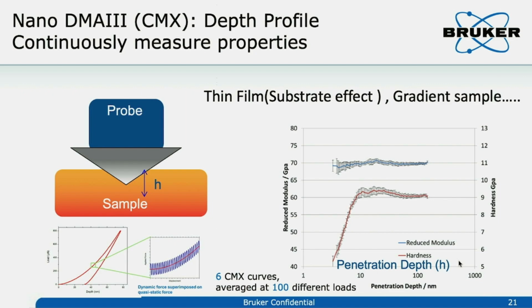So if we look at the load function, it's just like the normal nanoindenter: load and unload. But we added an oscillation in the load segment. If you zoom in here, you can see there is a high-frequency oscillation during the indentation. If we treat one oscillation as one small indentation, then we can calculate the stiffness from one oscillation, then we can calculate the modulus and hardness for each small oscillation here, right? So this allows us to measure the modulus and hardness by depth continuously, right? So we call this the mechanical properties depth profile.